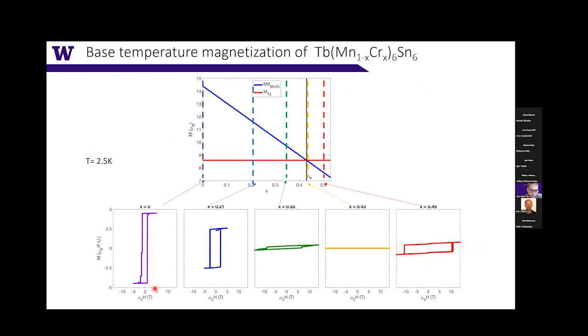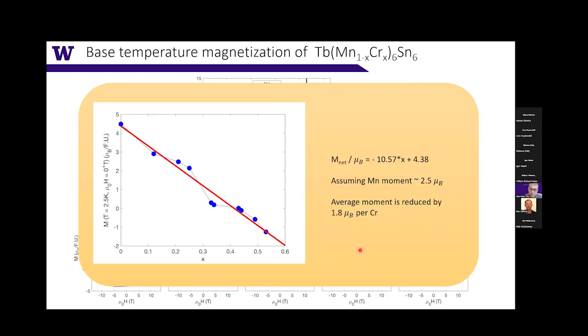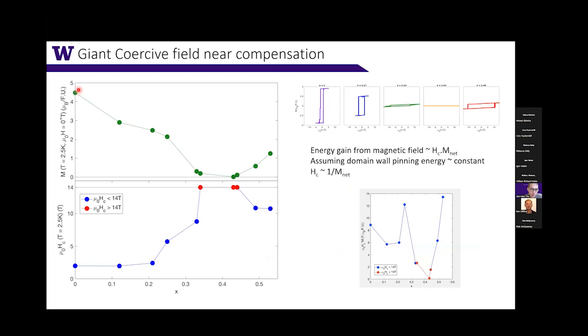The coercive field is maybe of the order of 1 to 2 Tesla, but it quickly increases as the magnetization vanishes. Here I'm plotting the saturated magnetization at the base temperature as a function of doping, and you can see it keeps decreasing, getting to 0, and then coming back again. And then the coercive field almost diverges at the point where your magnetization vanishes.